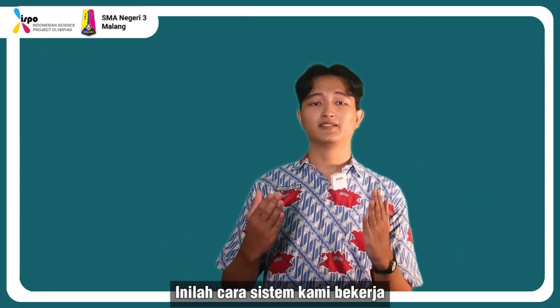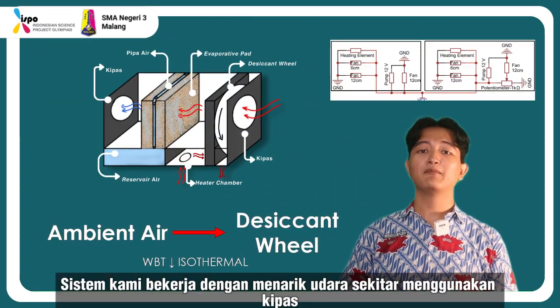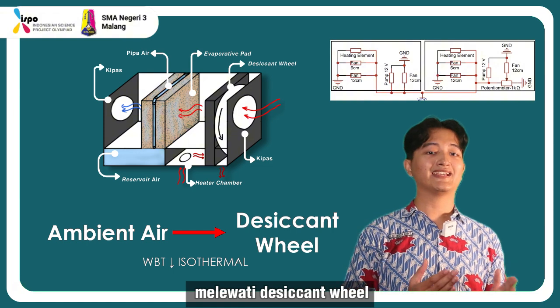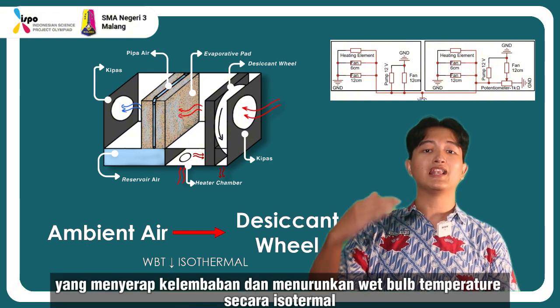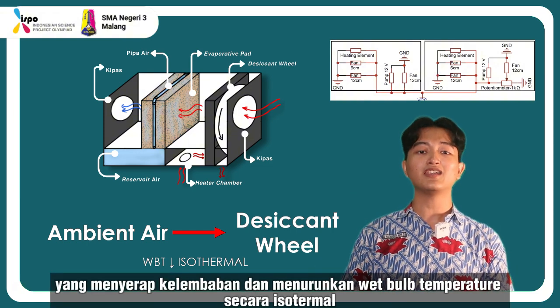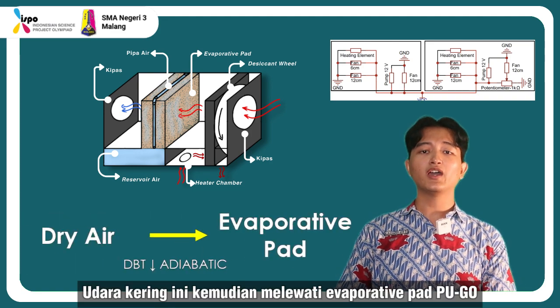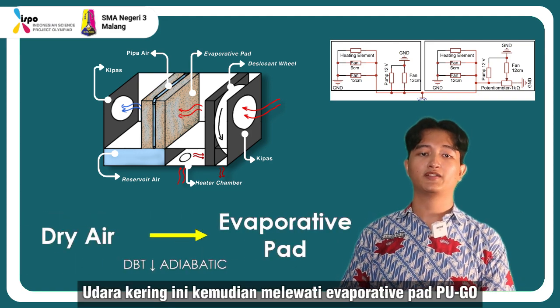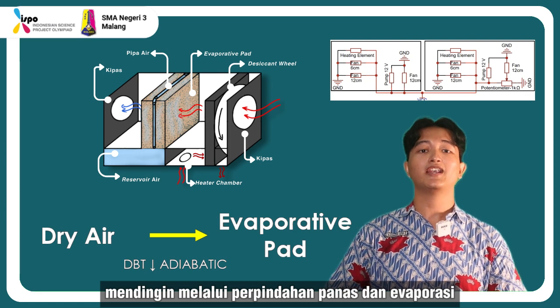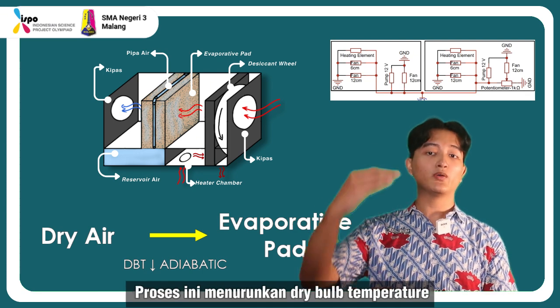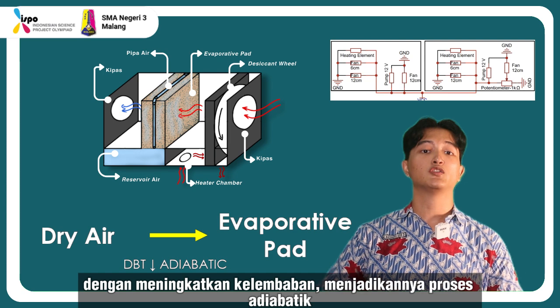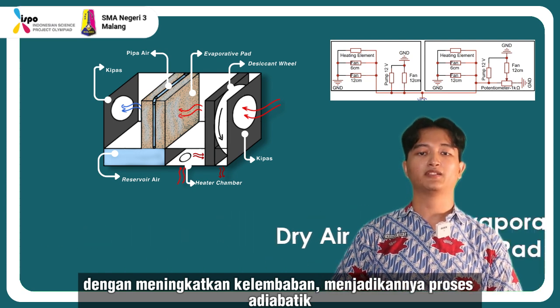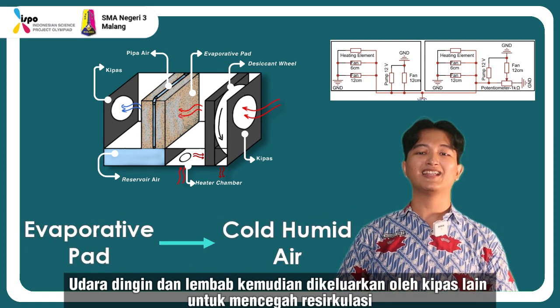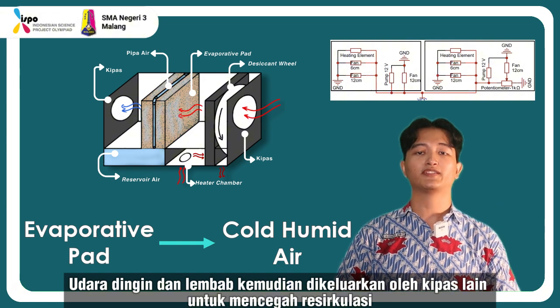And here's how our system works. Our system draws in ambient air with a fan, passing it through a desiccant wheel that absorbs moisture and lowers wet bulb temperature isothermally, creating dry air. The dry air then moves through the PUGO evaporative pad, cooling via heat transfer and evaporation. This process lowers the dry bulb temperature by raising the humidity, making it an adiabatic process. Cool humid air is then expelled by another fan to prevent recirculation.